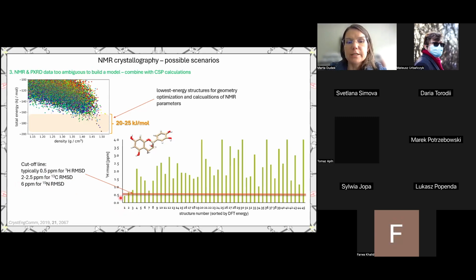As you can see here, there is only this one structure, and it is also the structure with the lowest energy. If we find something like this, we can safely say that we found a model, a crystal structure, which sufficiently well represents the real crystal structure that we have in our laboratory. So in that way, we can obtain results using solid-state NMR data in a similar manner to those from single crystal X-ray diffraction crystallography.